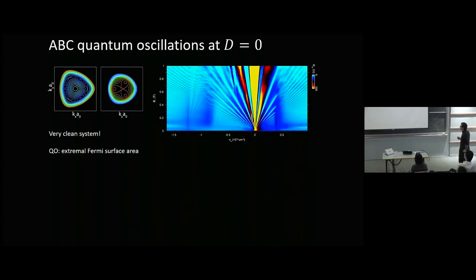And what we can do is use this to map out the Fermi surfaces in these structures and try to figure out exactly how well we understand the band structure, what's a correlation effect, what's not a correlation effect. So quantum oscillations probe the extremal Fermi surface area. You usually do this by taking Rxx of 1/B and doing a Fourier transform. Because we vary the density in these systems, it's useful to normalize the frequency that you get, which tells you the area, by the Luttinger volume, so that you're actually measuring the fraction of the total Luttinger volume encircled by a given quantum oscillation.